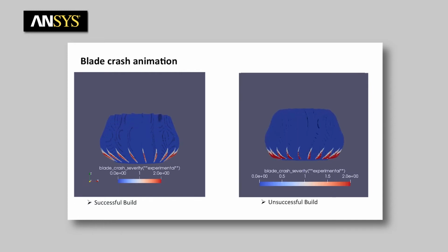So we basically went in and said, okay, if we superimpose the distortion, we can see that in red here, it's moving quite a bit in one direction. If we zoom in, let me zoom in somewhere on this part, maybe down here in the bottom, you can see that basically the fin is moving the entire width of that fin out of compliance. So now you're not going to have the same aerodynamics. And indeed,